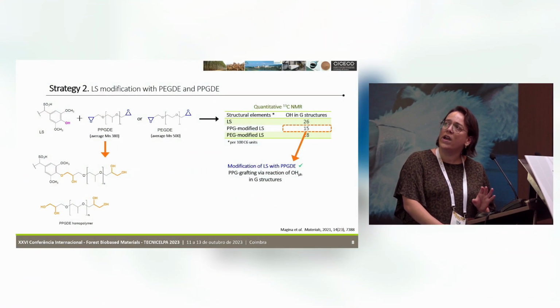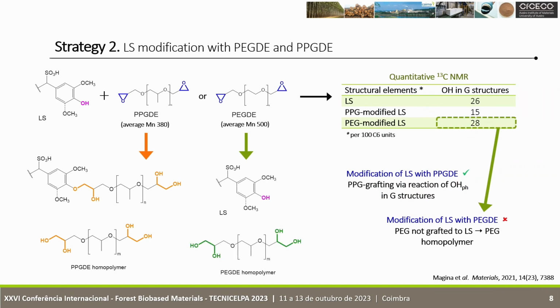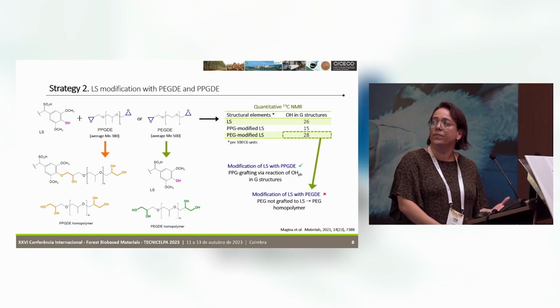In the case of the reaction with polyethylene glycol derivative, it seems like no reaction occurred, because there was no difference in the number of hydroxyl groups. The results then suggest that the final product is made of unmodified lignosulfonates and polyethylene glycol homopolymer.